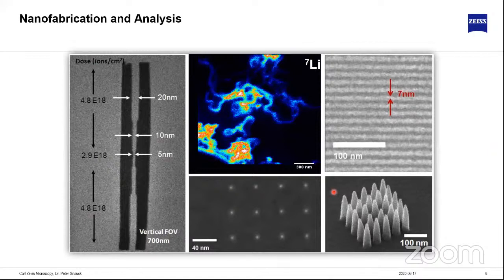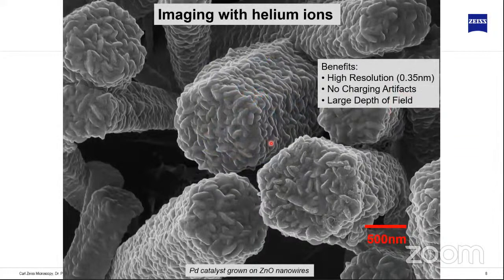Okay, if we use a little bit higher currents, we can also use the ions for material modification. So we can, for example, generate small ribbons in graphene, down to 5 nanometer thickness. We can create nanopores in 2D materials, which are of single-digit nanometer size. We can do ion beam lithography on photoresist without any proximity effect, with very high resolution. If we're adding a gas injection system, we can also deposit materials, so we can do 3D build of all kind of different structures. And if we're using higher mass ions like neon, for example, we can generate secondary ions, and we can do SIMS, secondary ion mass spectroscopy, and do nano analytics on all kind of different materials. Okay, I'd like to focus on the imaging part a little bit in the beginning.